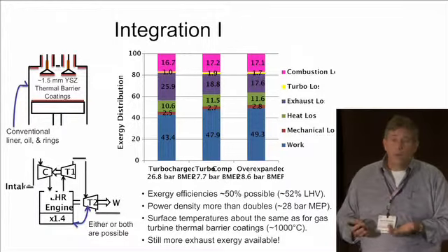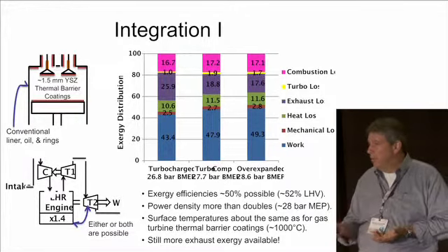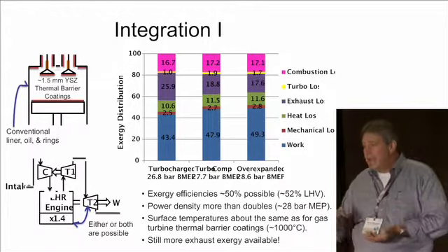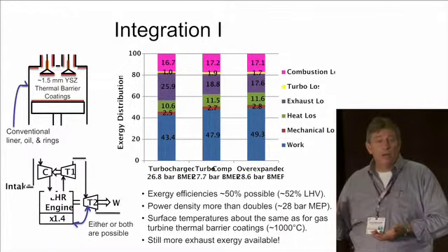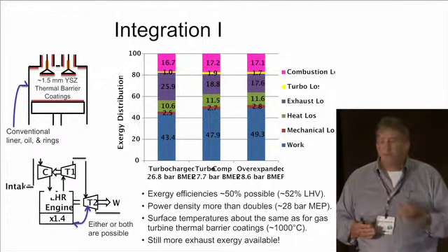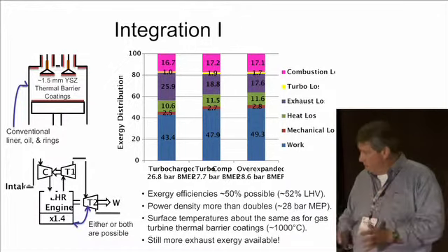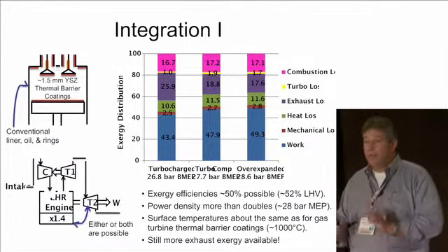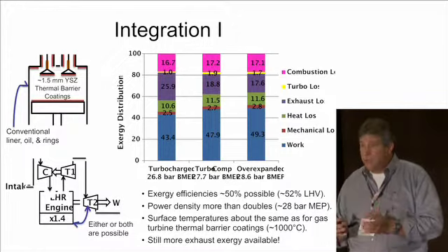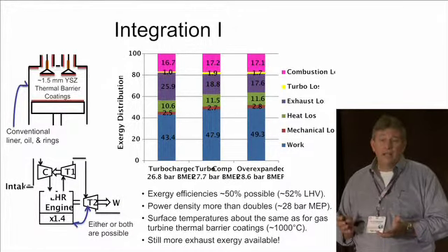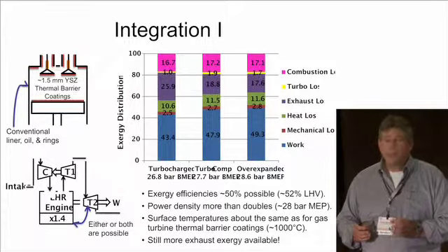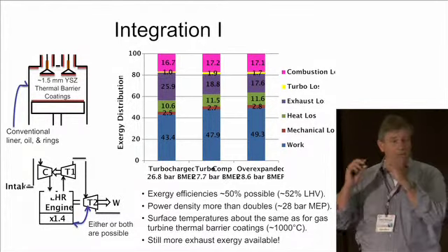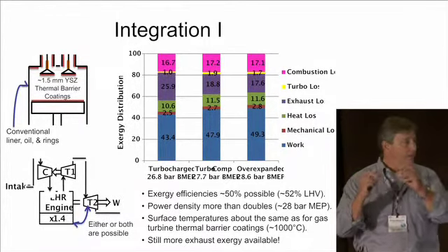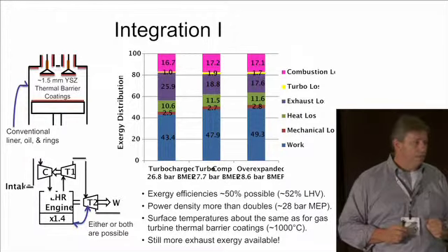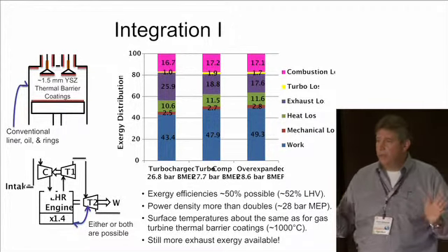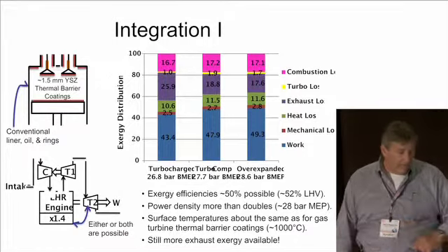But basically, we've taken coatings out of gas turbines, the same thermal barrier coatings that you have in a GE gas turbine, 8YSZ, spray that on, about 1.5 millimeters thick. And if you do that everywhere except the sidewalls, which is where you need the oil, where you need cooling, where the rings go, all that good stuff, leave that alone, you can cut the heat transfer by 50%. Turns out most of the heat transfer is not on the sidewalls. It's up at top dead center where the temperature's high, the convective coefficient is high. That's where the big heat flux is. Don't mess with the lubrication, don't mess with the rest of the system. But it allows you to take about half of that back.